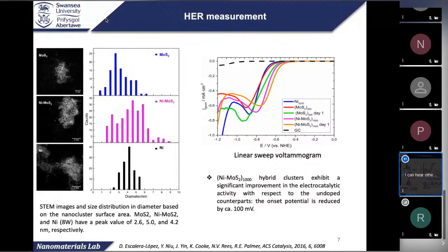We tested the hydrogen evolution reaction for all those three materials. On the right-hand side, you have the LSV, the linear sweep voltammetry of this reaction. What we found is that the nickel-doped MoS2 has enhanced activity, shifting the onset potential by about 100 millivolts, which is good, but not as good as we expected. So we realized that the problem might be the crystallinity of the cluster. All these theoretical calculations are based on crystalline MoS2, but what we made is amorphous or polycrystalline.